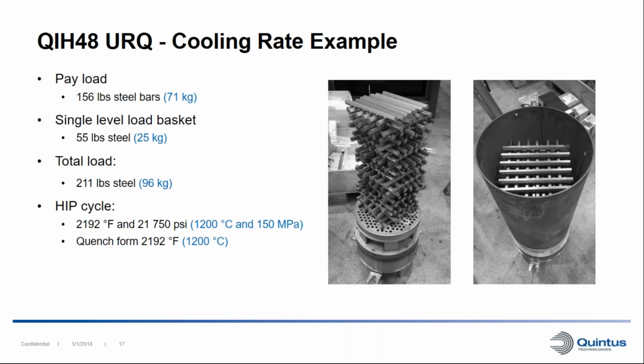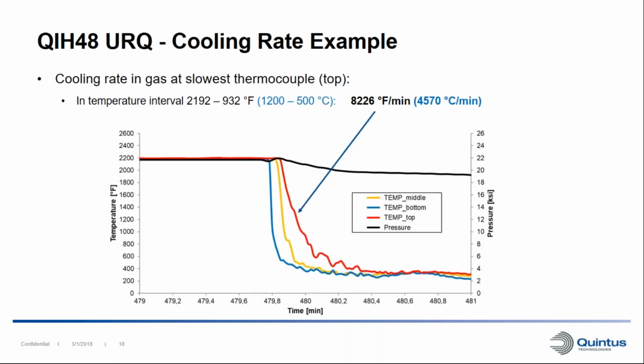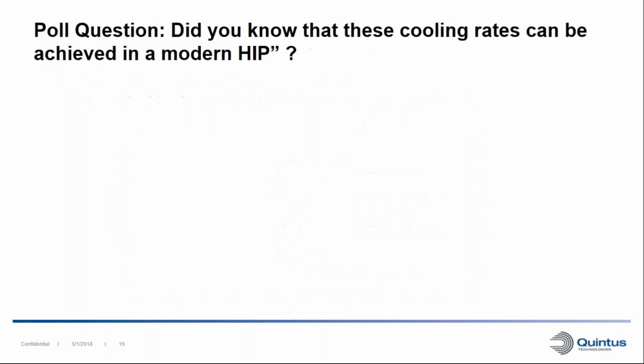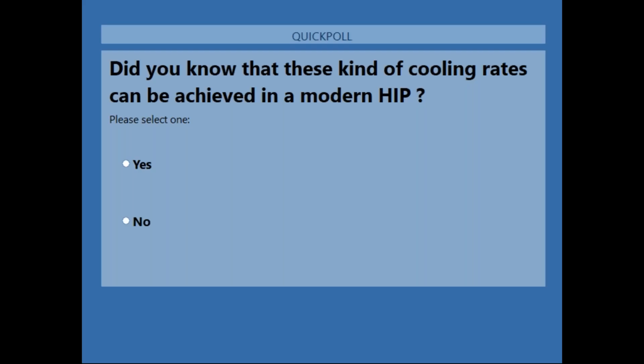The HIP cycle for this test was just below 2200 degrees Fahrenheit and just below 22,000 psi. And we were quenching directly from the HIP temperature. And here we can see the results from this test. If we look at the temperature interval shown here, and if we look at the thermocouple in the furnace that shows the slowest cooling rate, we can see that we can achieve above 8,000 Fahrenheit per minute, which is kind of impressive.